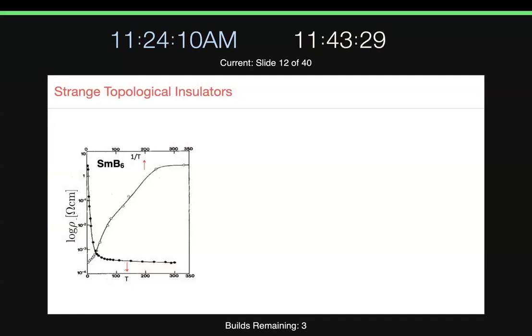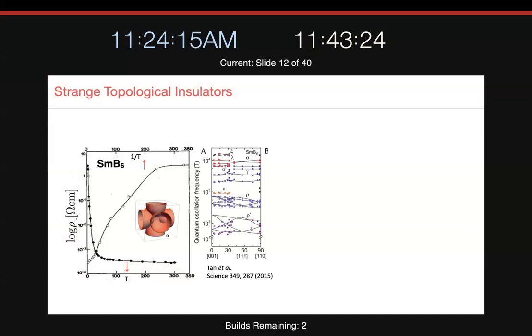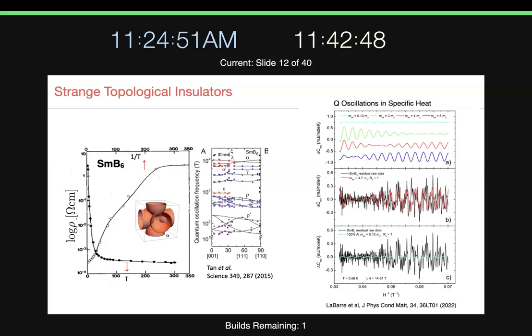This is samarium hexaboride, which is a topological insulator at first blush. But it has the bizarre property that it has a linear specific heat in its insulating state, and we don't know what produces that. And furthermore, some experimentalists have seen de Haas-van Alphen oscillations in the magnetization, and these oscillations can be traced out to give a Fermi surface. It looks as if there are unhybridized d electrons in the system. And these data have been confirmed independently by the group of Art Ramirez, first discovered in Cambridge.